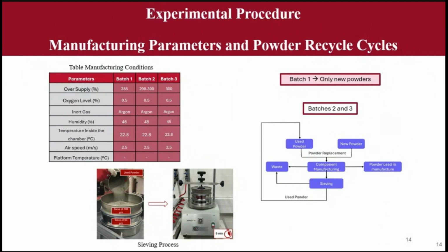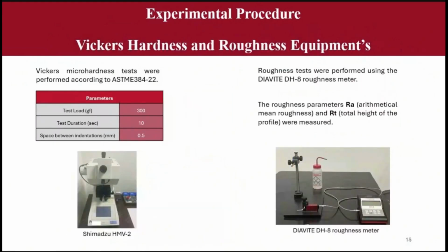The condition was: batch 1 only used new powders, batch 2 used two-times sieved recycled powders, and batch 3 used three-times sieved recycled powders. And all the other parameters were the same, because it is too many parameters together.